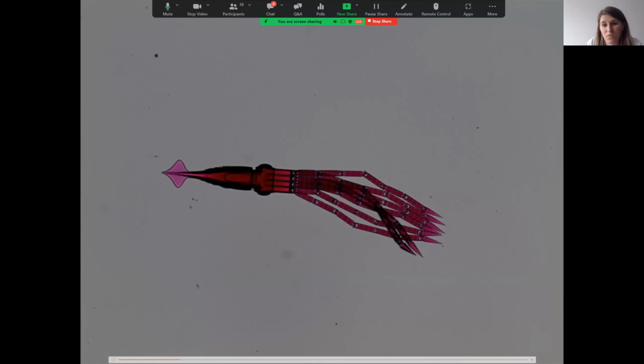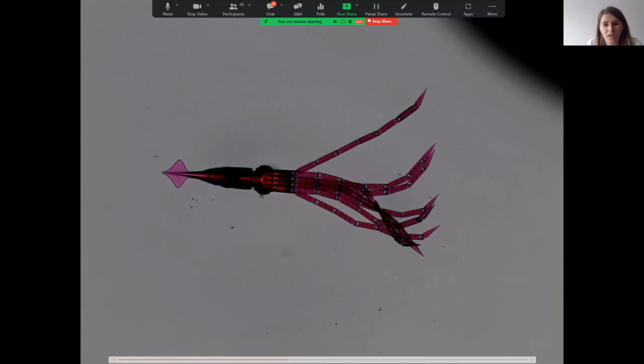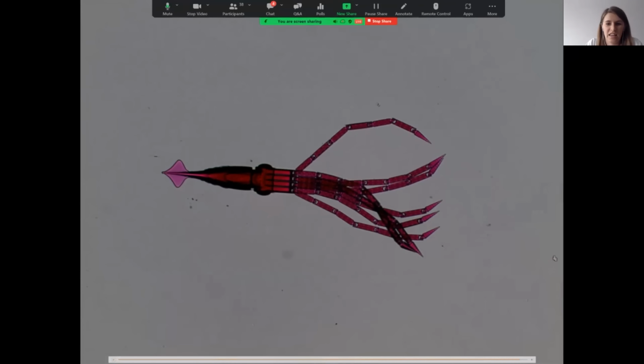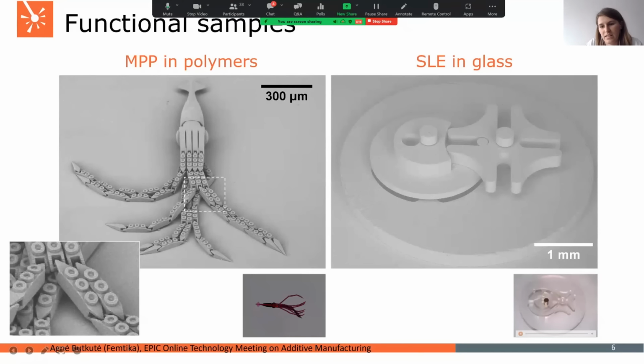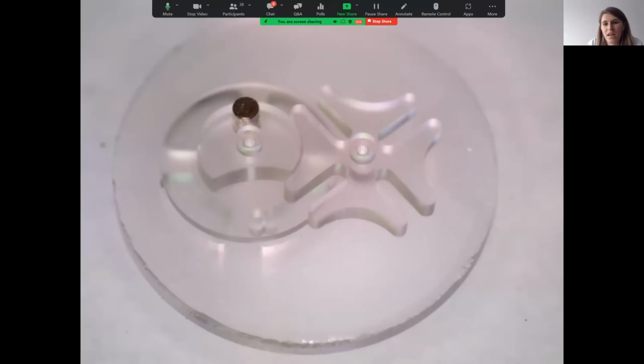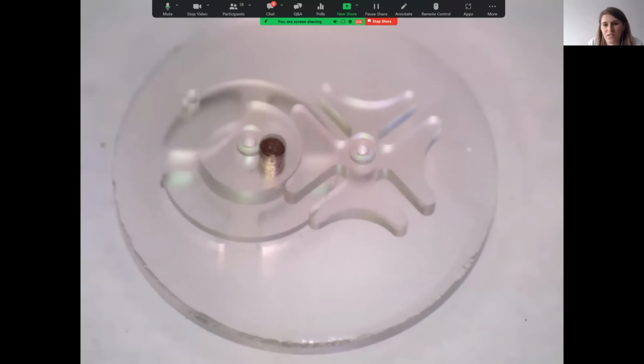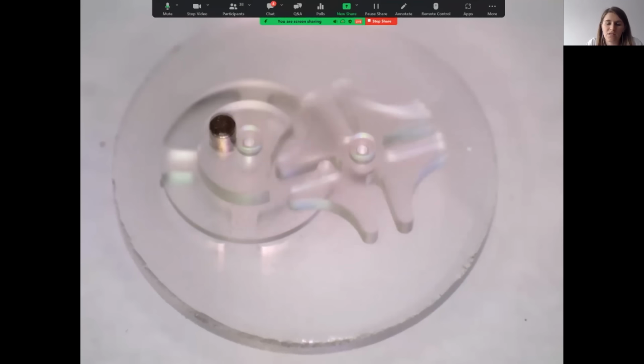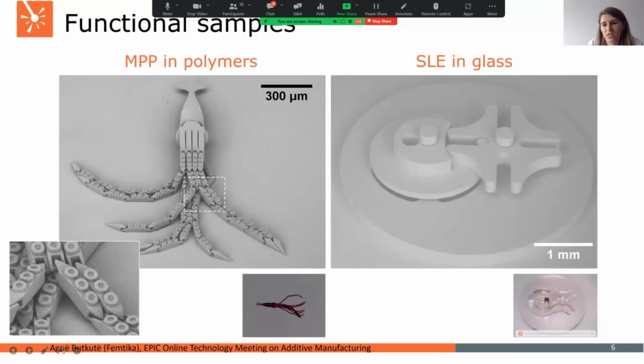Here you can see a polymeric structure which was just polymerized, and you can see that the tentacles of the squid are moving freely in the water. Another example is a glass structure. This is called a Geneva mechanism. Again, this structure was made directly out of a single piece of glass, just by inscribing the modifications. We place a magnet on top of the mechanism, and the whole mechanism is placed in an external magnetic field, and that way the movement of the structure is automated. This just represents the possibilities. It shows that these techniques are quite suitable for various micro robotic solutions.